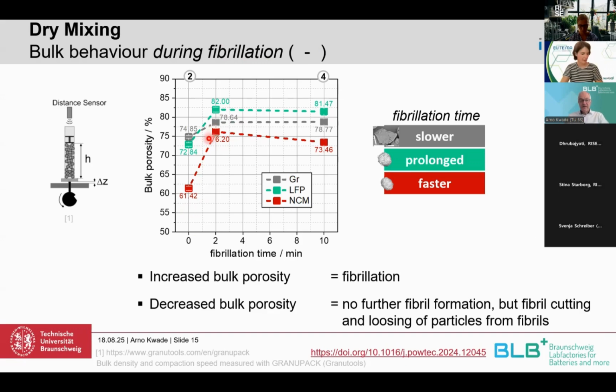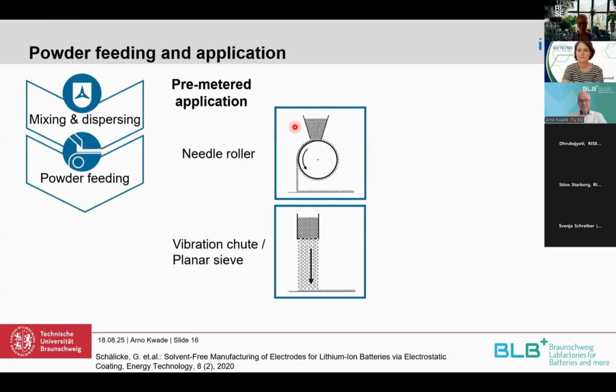And you also see that after 2 minutes, there's no further fibrillation. It seems that there's more, let's say, degradation, or a fibrillation decrease, at least in the length, so that we have a more constant or decreasing porosity of the powder.